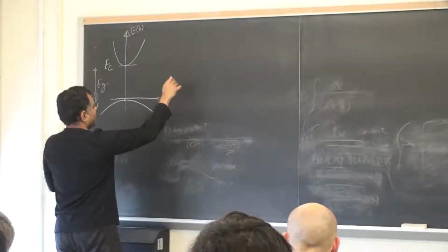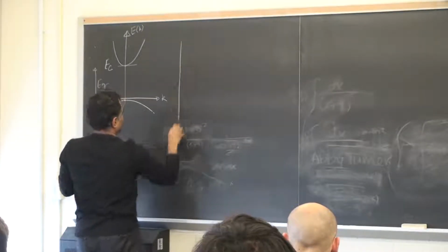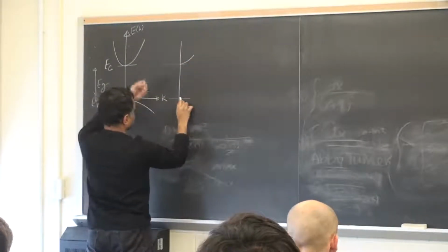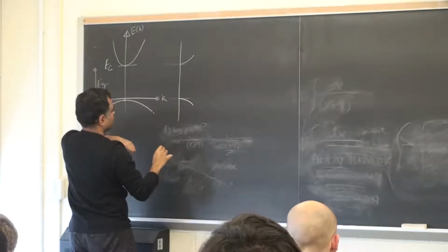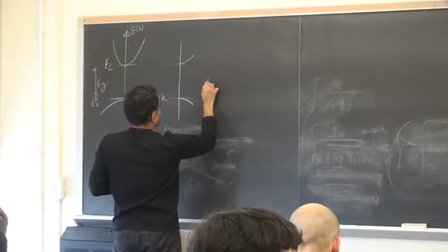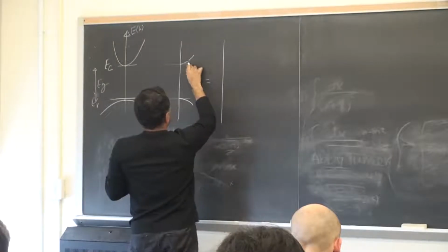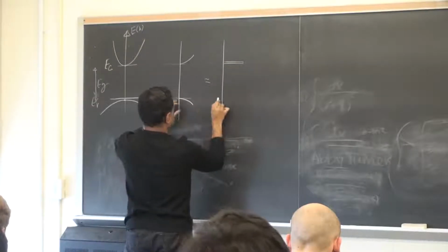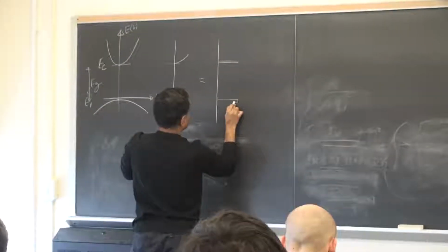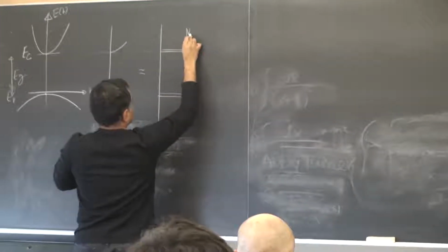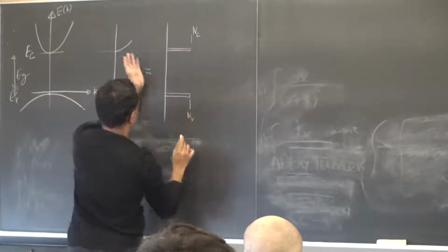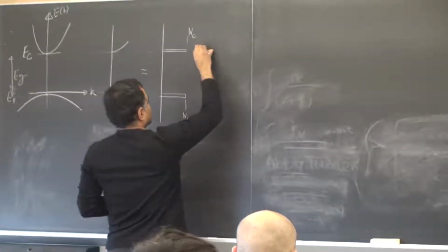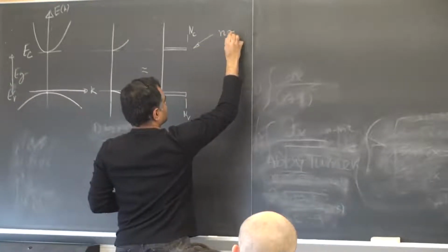We then discussed that starting from the band edge, the density of states will go as the square root of energy in 3 dimensions. Similarly, there will be a density of states in the valence band. If you make certain approximations, you can bunch these into one band edge density of states, with the value being N sub C, and another with the value being N sub V. Once I do that, I can write that the number of electrons in the conduction band is roughly